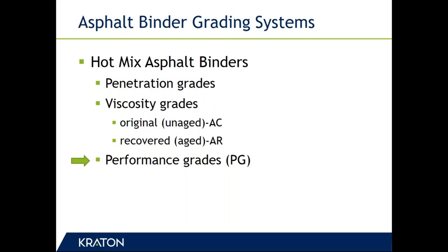Viscosity grades came on after that in most of the United States, and those were primarily based on the viscosity of the original asphalt, that is, the material that hasn't been aged. And that's analogous, I guess you could say, to motor oil gradings, because it's based upon the resistance to flow at a reference temperature, in this case, 60 degrees Celsius or 140 degrees Fahrenheit.